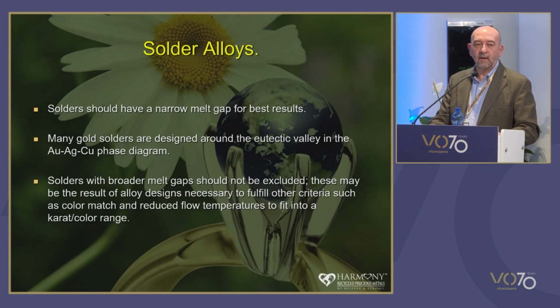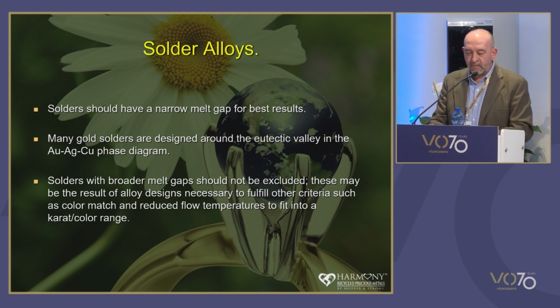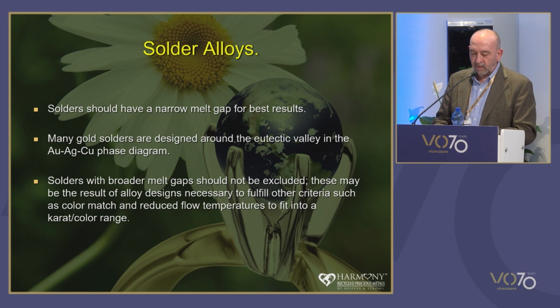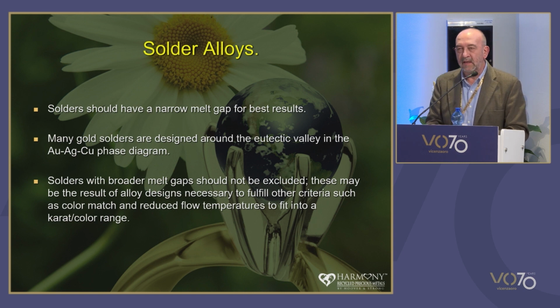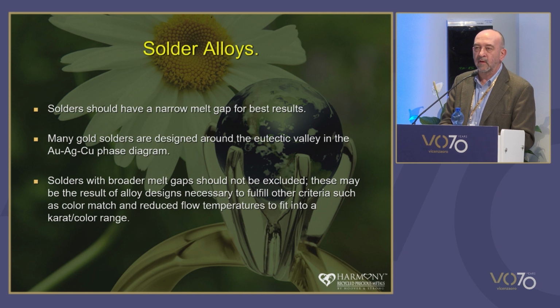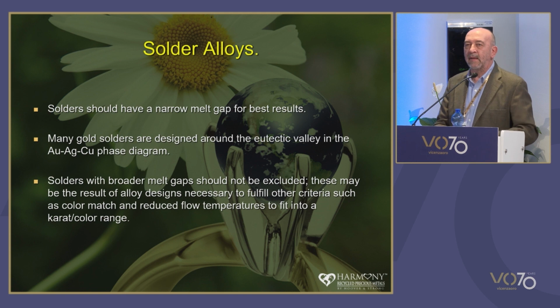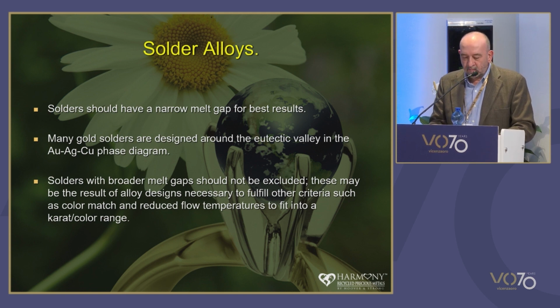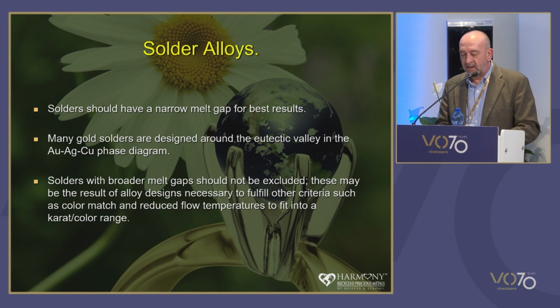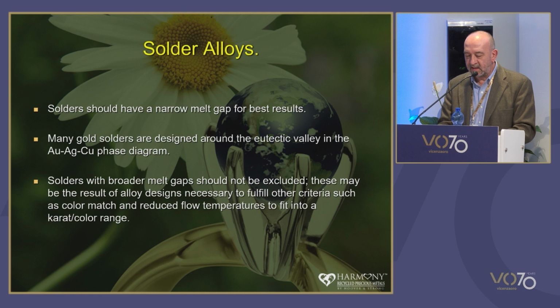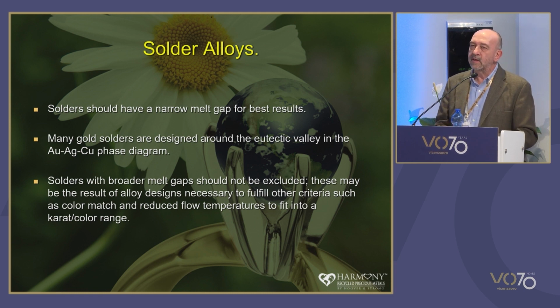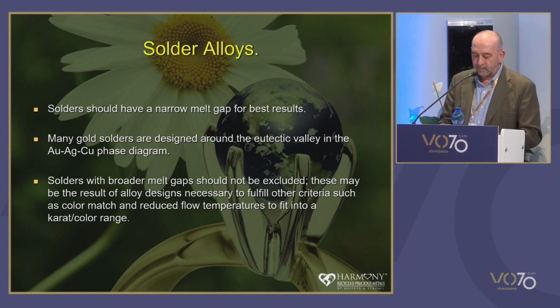Next slide. Here we go. So it's generally accepted that solders should have a narrow melt gap for the best results. For gold solders, this often means they are based around the eutectic valley in the gold-silver-copper system, and this not only keeps the melting temperature low, it also keeps the melt gap narrow. Some solders do have quite broad gaps, but this is usually a design around color considerations and where they sit in the soldering process. Color match can also be difficult the further away a solder is from the parent metal in melting range.